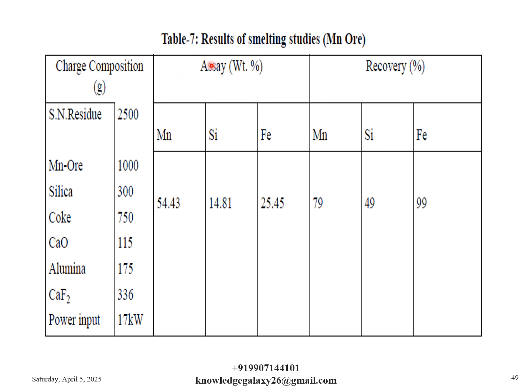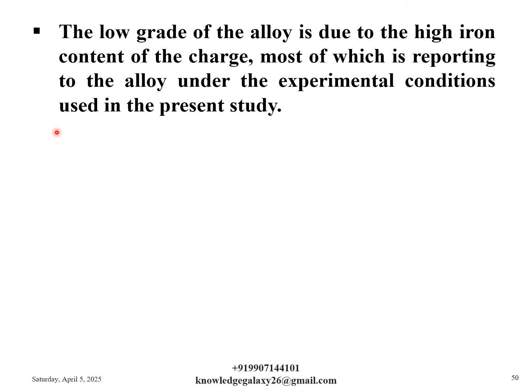So this is the table 7, which shows the results of smelting studies for blending with manganese ore. So this is the result. You can pause the video and observe the contents. As is depicted in the above table, the low grade of the alloy is due to the high iron content of the charge, most of which is reporting to the alloy under the experimental conditions used in the present study.